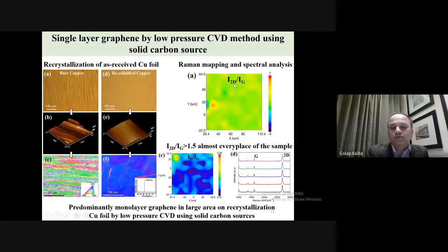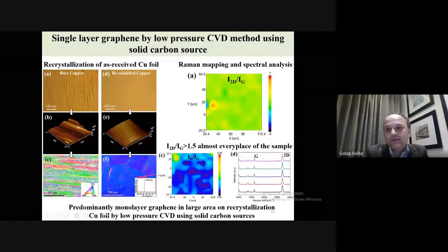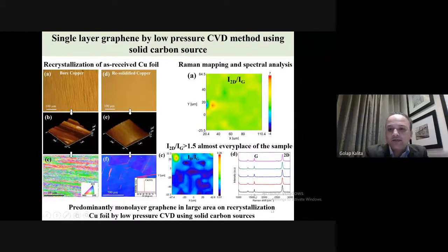The 2D peak is the graphene recognizing peak. This is a Raman analysis actually. The 2D peak comes around 2700, and the graphitic G peak is around 1600. In Raman spectra, you will always see that the 2D peak is more than twice the G peak for a monolayer graphene. And this is just the defect peak, the D peak. We can see that it's uniform throughout the measured Raman spectra of the graphene synthesized on resolidified copper foil. So we can get very highly uniform monolayer graphene on resolidified copper foil.